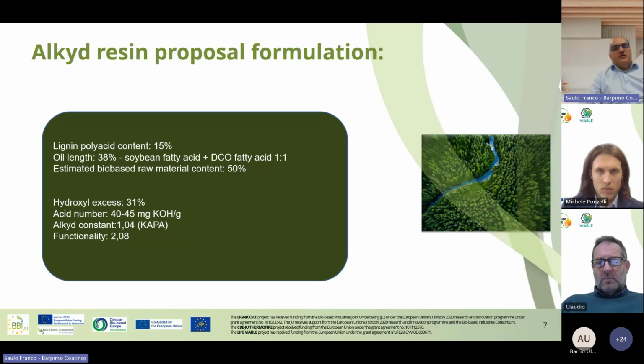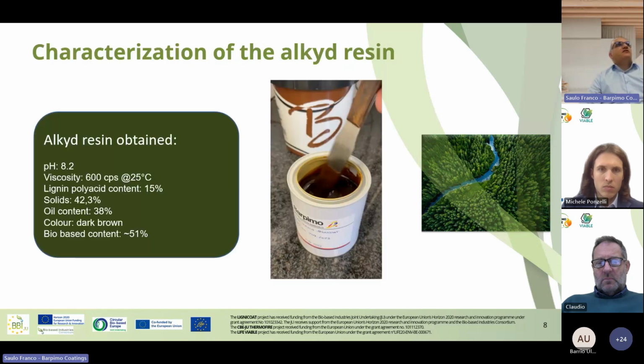As a result, we obtained an alkyd resin with a 42.3% solid content, 38% oil content, dark brown color, lignin polyacid content 15%, a viscosity of 600 cPs at 25 degrees, a pH of 8.2, and a bio-based content of about 51%.